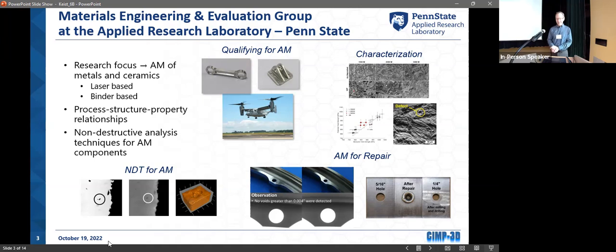In this case, for the titanium, we were in parity and slightly above for fatigue results for this particular process. But titanium is really good. It works pretty well with additive. Some alloys may not work very well, since we're building with a powder and a lot of contaminants can get on that powder. For some metal alloys, it's a little more difficult to work with additive because of that.